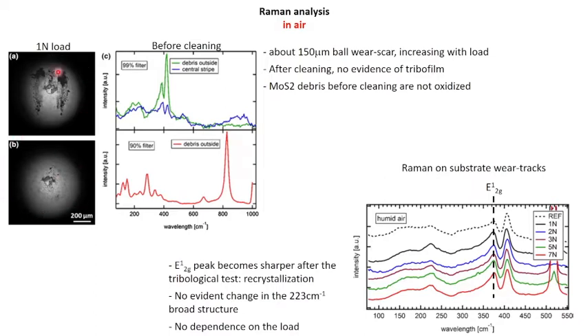Well, before cleaning the counterbody, we performed a Raman analysis on this region where the debris are present and in the wear scar. And what we obtained is reported in this graph here, where the green spectrum corresponds to the region with the presence of the debris, while the blue spectrum represents the analysis on the wear scar, so in the middle of the wear scar.